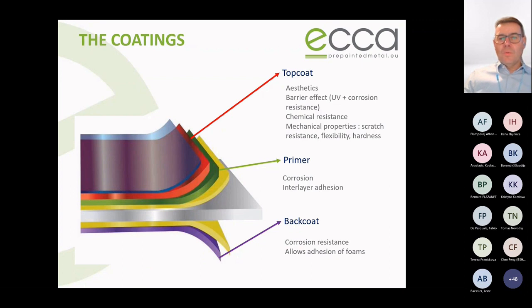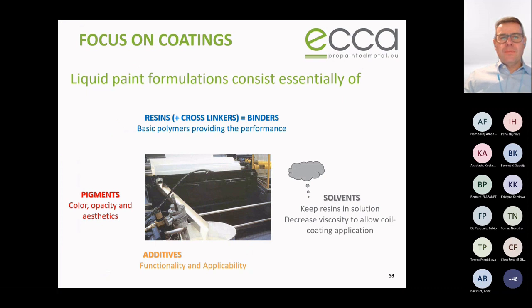On the back side of the steel or aluminium belt, we apply back coats, and their function is to ensure corrosion resistance, but also allow adhesion to foam and glues. Liquid paint formulations consist essentially of resins, which in combination with cross-linkers create binders. These are polymers which in a dry or cured form are the main components of coatings. They contribute to film build, adhesion, hardness, flexibility, durability, appearance, as well as resistance to chemicals or other factors like, for example, heat. Generally, they provide performance and can also add to functionality.